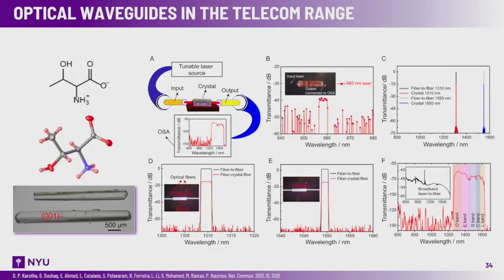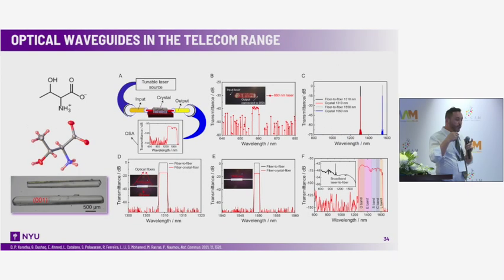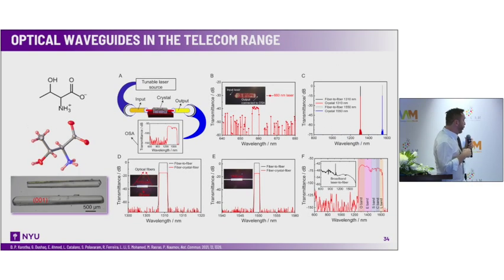Now, all of the information that we receive over the internet comes not in the visible regime, as you know, but comes in the near infrared. So our most recent endeavor was to shift from the visible range to the telecommunication regime. In this particular case, we have a very simple amino acid crystal, which happens to be also very hard, with Young's modulus about 40 gigapascal. We transduce near infrared light, and we can transfer information in the telecom regime.